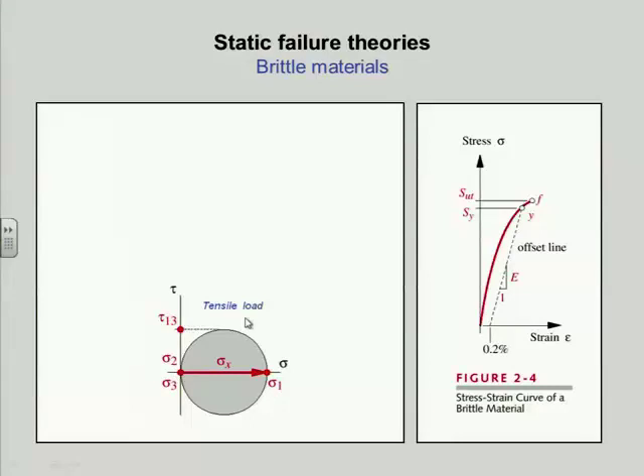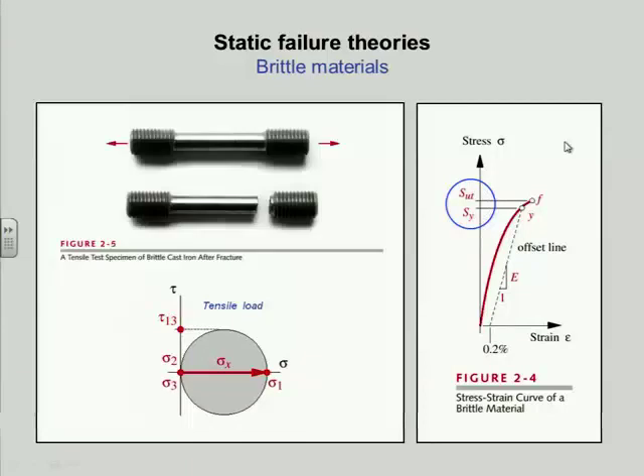So the tensile stress diagram, Mohr's circle for the tensile test in the brittle material looks just like the one for the ductile material, but the material is behaving in a different way. Notice how close the ultimate tensile strength is to the yield strength, and that's not true of soft ductile steels. There'll be quite a difference between those two numbers, maybe 30,000 to 50,000 psi for a 1020 steel or something like that. There's the same picture of the specimen I just showed you on the board with a before and after being pulled. That's cast iron, gray cast iron.